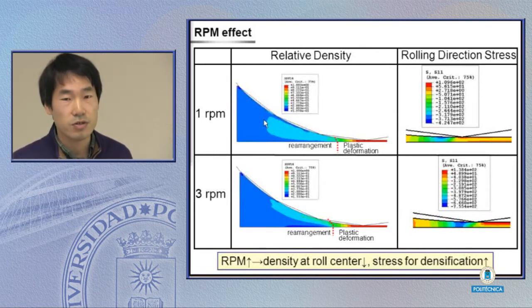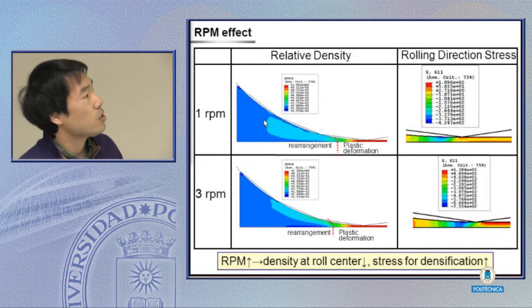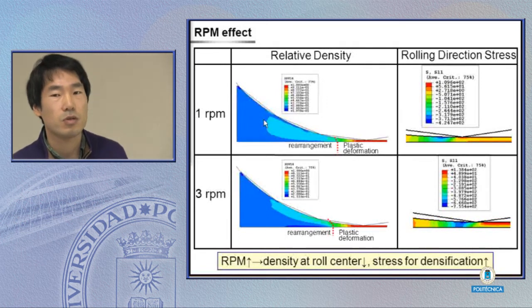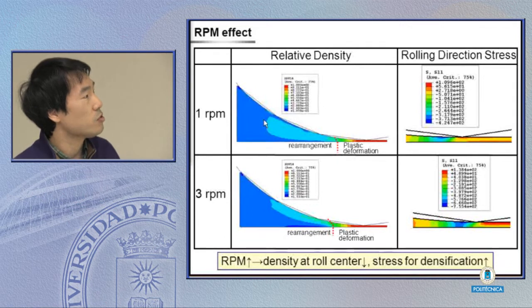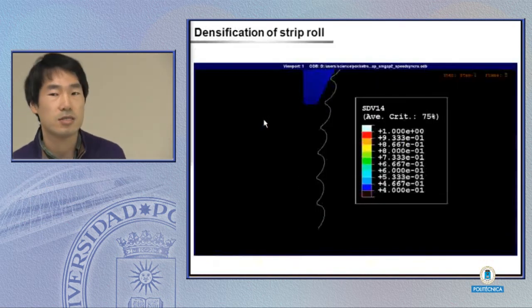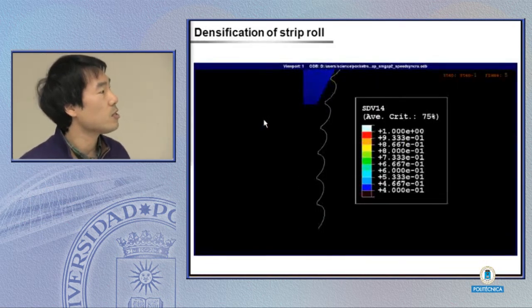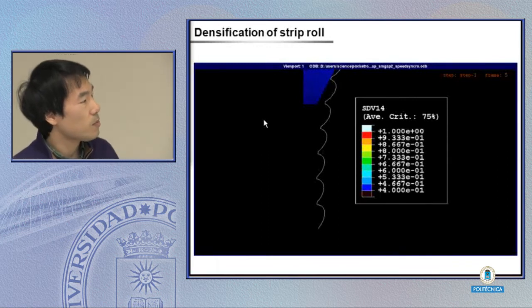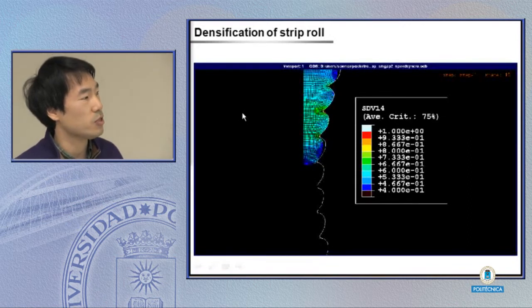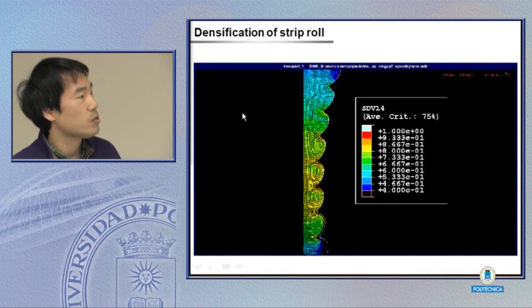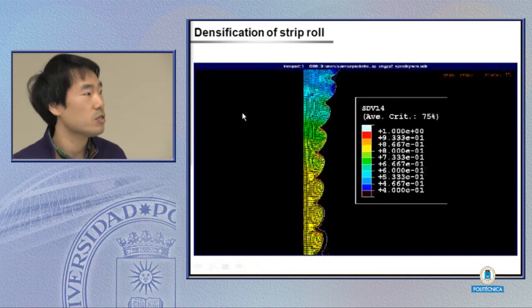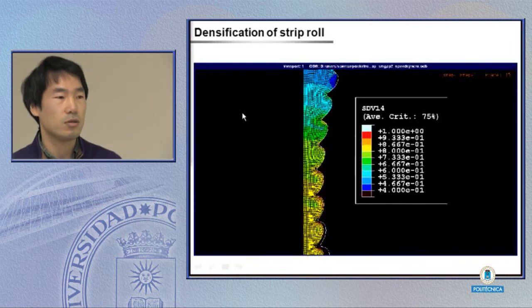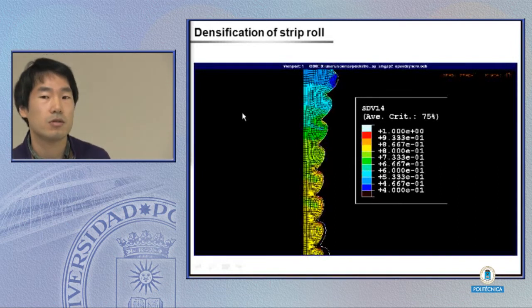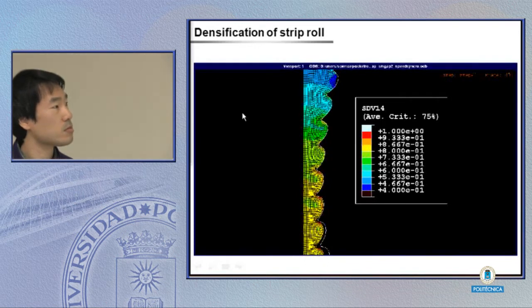So here is the major result of this simulation. With the low RPM, low speed of the rolling compression, all the powders inside the rolling can be compacted nice and smoothly. However, with the higher speed of rolling, only the powders near the rollers are compacted, and it gives huge residual stresses. So, with the high speed of rolling compression, you will produce a very unstable compacted powder.